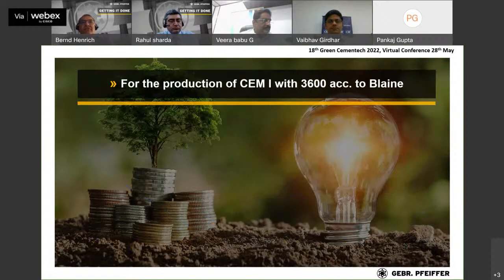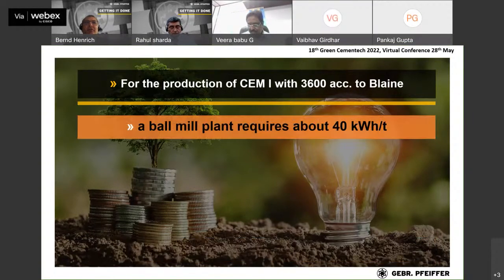This is a general view of CEM I, which means OPC, OPC at 3600 Blaine, which is used all over the world. Sure, we will later come to the point of substitution of clinker and what is the effect of this. But when I look at an OPC, a normal cement production, then the average figure is 40 kilowatt hour per ton when doing this grinding in a ball mill system.